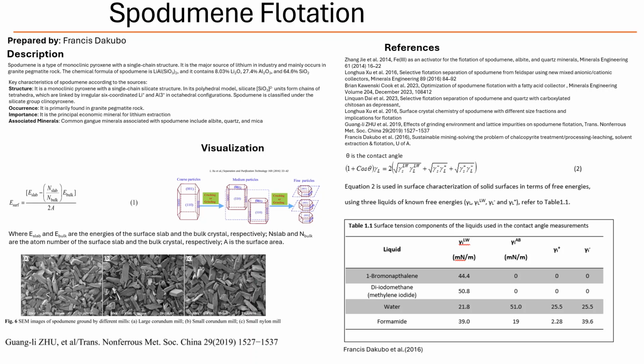But it's not just the chemistry, it's the physical shape too. The size and flatness. Right. Particle size and shape definitely play a role. One study found, for instance, that a big corundum mill made particles that were finer, but also longer and flatter. Compared to smaller corundum mills or nylon mills, which tended to produce more sort of flaky particles. And why does that matter? More surface area. Partly more surface area, but also which surfaces are exposed.